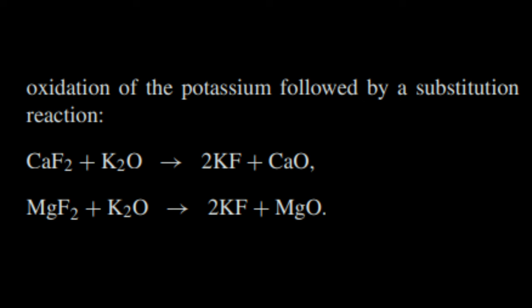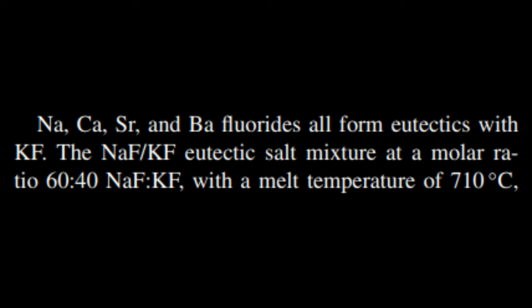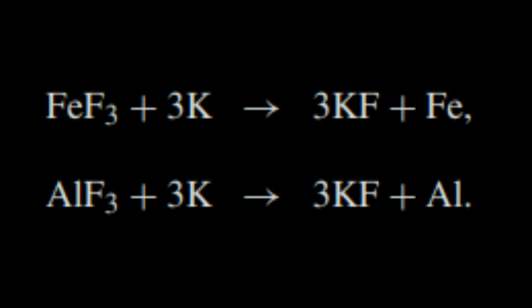and we are already going to use electrolysis to recover the potassium from the fluoride, so this is sort of another version of the calciothermic electrolysis approach. It makes sense to electrolyze this potassium fluoride in a solution of sodium fluoride, which will lower the melting temperature. But we still have the issue of the aluminum and iron being alloyed together.